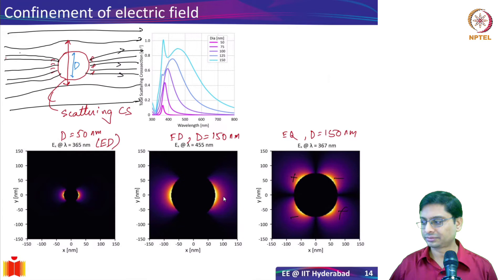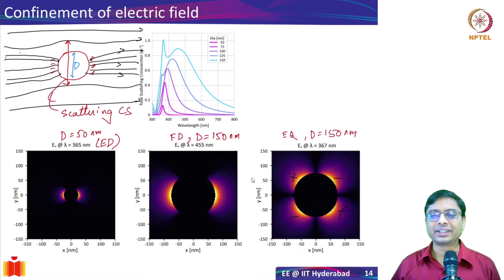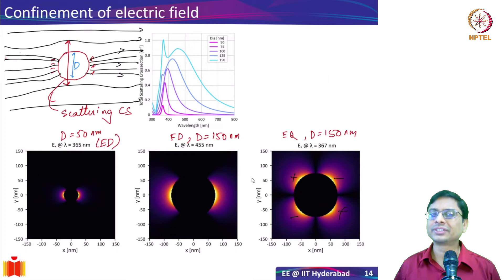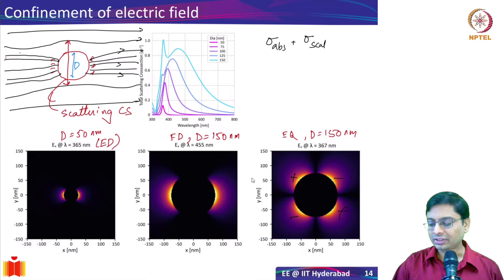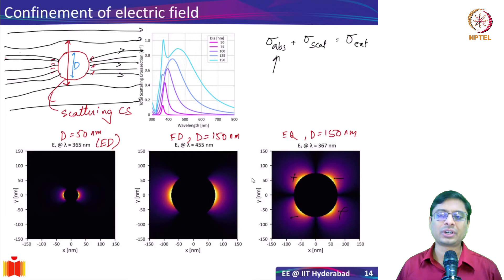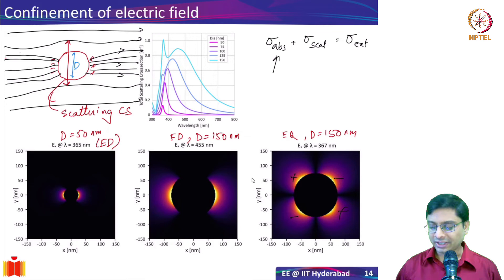Why is the resonance broadening? It turns out that as the size of the particle increases, it is able to scatter more efficiently — so scattering losses are higher, and therefore the resonance is broader. If you compute the joule losses, they are not that significant. Using Mie theory, you can compute the extinction cross section: sigma_extinction = sigma_absorption + sigma_scattering. Looking at the absorption cross section specifically, it is not significantly broadened — it's just that scattering losses are high, making the resonance broader.